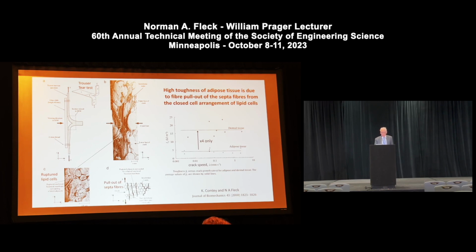And the consequence is that the fracture toughness, or the toughness I should say, of adipose tissue is only a factor of 4 less than that of the dermis. So there's this remarkable result that this multi-phase interpenetrating lattice that we've all got is remarkably tough due to the presence of these interpenetrating fibers.